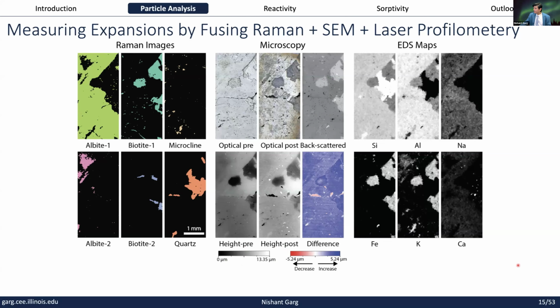Okay, so maybe I will answer this question. Essentially, if you pay close attention to quartz, Alessandra, can you confirm if my laser pointer is visible? Yes, it's visible. Okay, so if you look at this quartz phase, first you can confirm that this is indeed quartz, because if you look at the EDS maps, you can see the silicon is very bright and the aluminum is missing here. So you have high confidence that this is indeed a quartz particle.